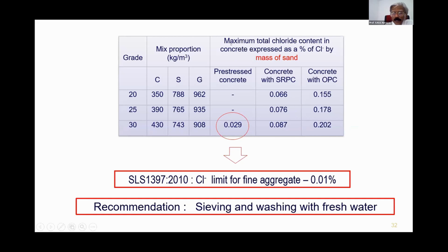So the most critical requirement is for pre-stressed concrete, that is about 0.03%, and the SLS standard limits the chloride to a maximum of 0.01%, very much less than the most critical requirement, that is to build up the confidence of the consumers. So the recommendation is we have to sieve the sand, remove the shells, the large shells, and we have to wash it with fresh water.